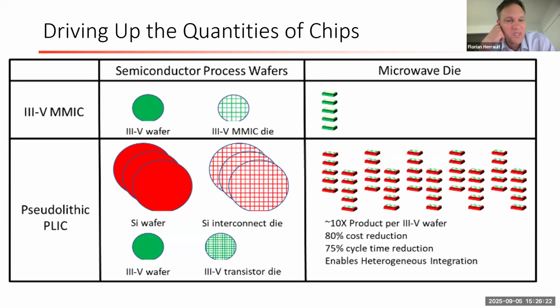That's because about 10% of the transistor chiplets are used in the silicon 200 millimeter wafer. So just to give you an order of magnitude, we might yield north of 50 to 80,000 chiplets per 4-inch wafer. We would use about 15,000 of those if it was a single technology integration into a 200 millimeter wafer. So the production output per III-V wafer is significantly higher, which speaks to our manufacturing efficiency, which speaks to our model of accessing those leading edge foundries towards commercial applications. And we can do this at lower cycle time and lower cost than monolithic solutions.